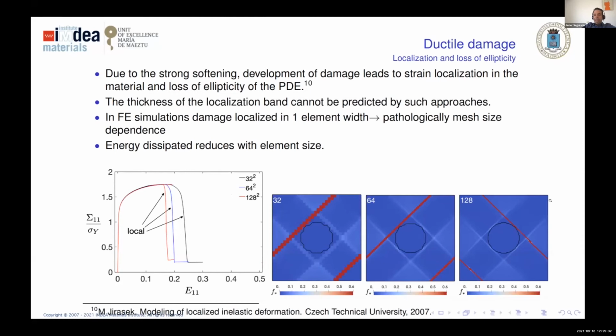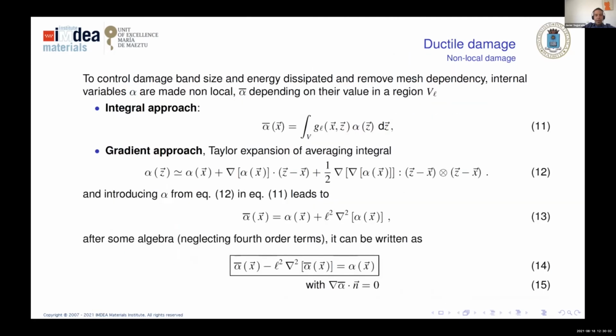Depending on the grid size, the damage bands become smaller and smaller. The consequence is that the energy dissipates in a different amount depending on the mesh size. So instead of having more or less the same behavior for different mesh sizes, we have a strong mesh effect that is pathological and unphysical, and that we cannot survive with. How can we solve it? There are different approaches, but we focus on using non-local models.